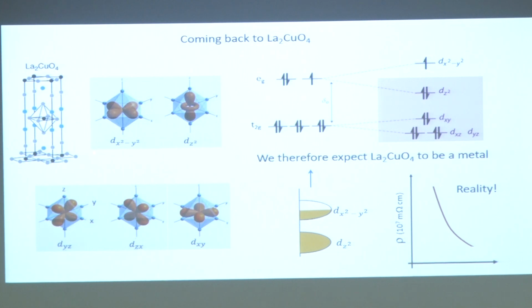So, compared to the free ion, by free I mean the D9 in vacuum, when you put D9 in an octahedral coordination, then the energy of x square minus y square and z square will go up, and that of these three orbitals will come down compared to the energy in vacuum, all right. And this set of these two together are called Eg orbitals, and these three together are called T2g orbitals. And now since we have 9 d electrons, T2g will be completely filled. So, this forms the core, and your Eg has 3 electrons, which is 1 less than the completely filled. So, therefore, it has one spin of 1/2, all right.